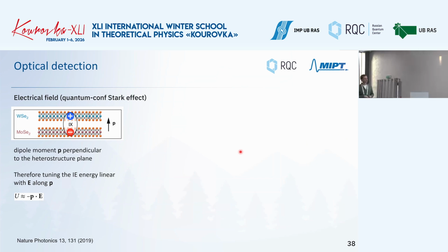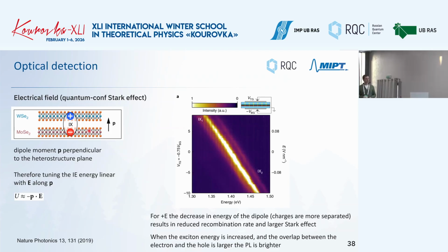Maybe just one thing to mention, that when people are doing the optical detection, just one slide, I will not go into details. When they do this optical detection, they rely on the fact that there are some specific excitons appearing in these moiré systems. There can be excitons within the layers, and then interlayer excitons between the layers. When you have these excitons and you apply an electric field, you have a quantum confined Stark effect, and you can move the wavelengths of your interlayer exciton with your gates. And this interlayer exciton serves as a probe for the crystallized state.